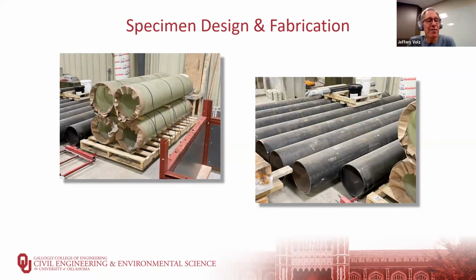We ordered the FRP tubes, which are 7 feet in total length, because again, they run from the top of the footing to the underside of the loading stub. And then the steel tubes are on the right. They are 11 feet long, because they are embedded 2 feet into the concrete base and 2 feet into the loading stub. Now that's actually more than the minimum embedment required for these columns based on the testing done to date, but we wanted to make sure that we did not have a pull-out failure for the columns.